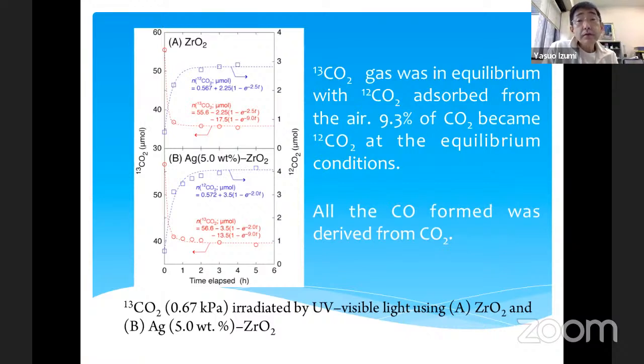So this is the exchange reaction, continuing from yesterday's talk. Time is the x-axis, and this is the amount of the gas. So 13CO2 gas was introduced, and it drops quickly because it adsorbs on our zirconia sample. At the same time, the 12CO2 evolved. These two types of gas are both CO2, but the isotope labels differentiate them, and they reach equilibrium,